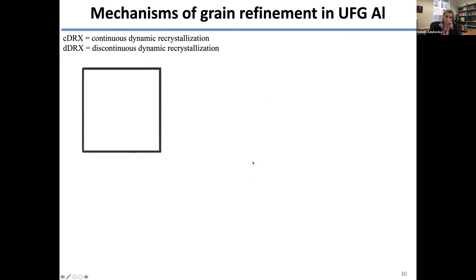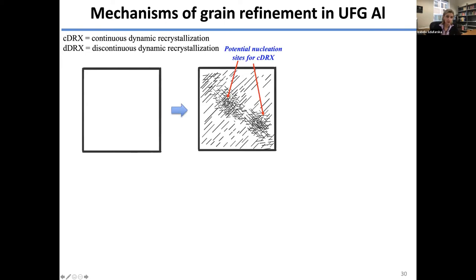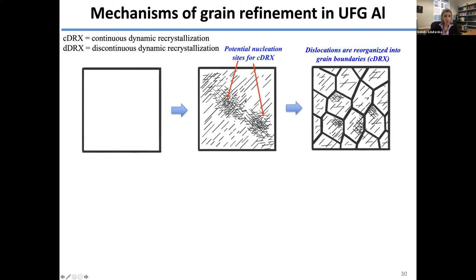The mechanism of grain refinement that we found in ultrafine grain aluminum is dynamic recrystallization. So there are two kinds of recrystallization mechanisms. There's a continuous and discontinuous one, and we found both. So here's how it works. Even if the grains are initially dislocation-free, dislocations are obviously introduced during the mechanical deformation, and they can organize themselves into cell structures and eventually form grain boundaries, right? This is called continuous dynamic recrystallization.